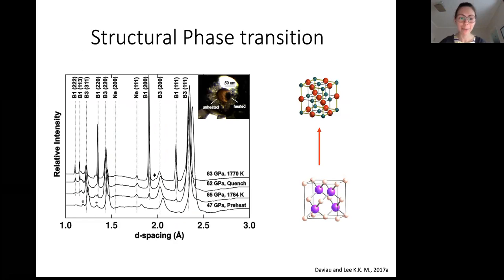So I have d-spacing plotted down here at the bottom versus intensity. And so this bottom pattern is the starting preheat pattern where we have loaded silicon carbide, that cubic B3 structure, along with neon, which is our pressure medium. And we find that as we heat it up, we observe the appearance of new peaks. So right here, a little bit below a d-spacing of 2, you can see the appearance of a really sharp new peak. And this is one of several peaks which correspond to a new B1 cubic rock salt phase, right?